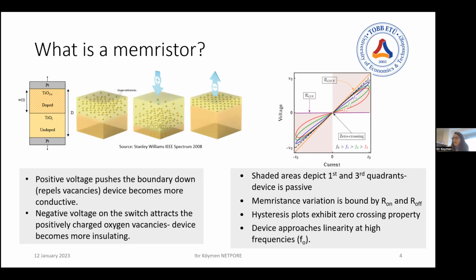And the way this memory property comes about is in resistance change, as I just said. So conductance changes according to the state of the device, and how this is controlled is through an input signal. In this case, the figure shows a voltage. So when a positive voltage is applied, oxygen vacancies spread out through the device, so the layer with oxygen vacancies becomes larger. So the device becomes more metallic, more conductive.